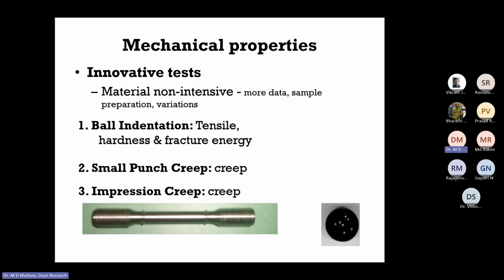So what you see on the right side is a small ball indentation test impressions made on a small sample size. You can see that each of these impressions gives you one data point with respect to the tensile or fracture properties of the material. So from a small piece, you can do a large number of tests.